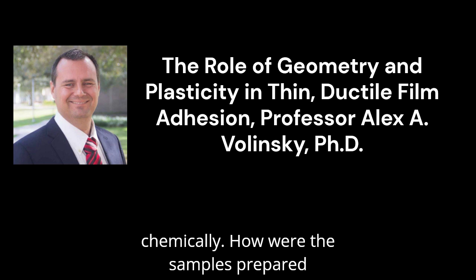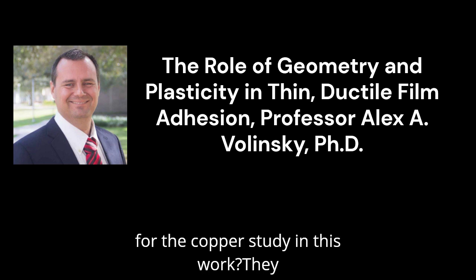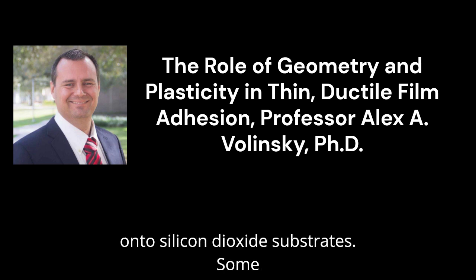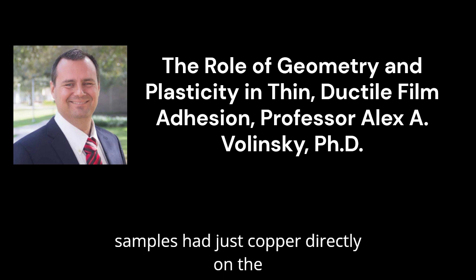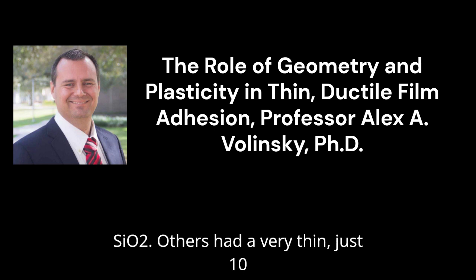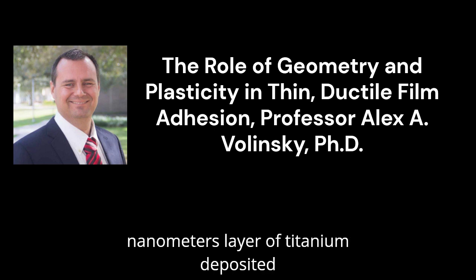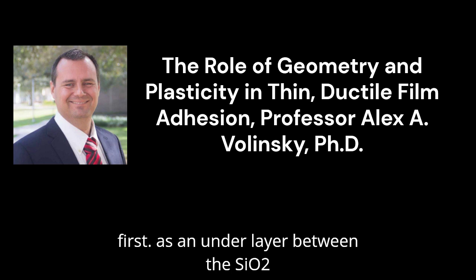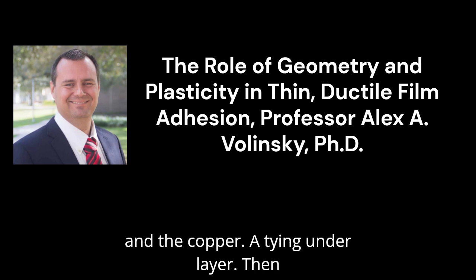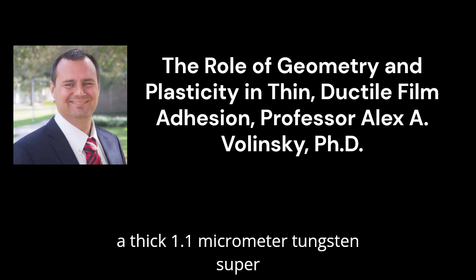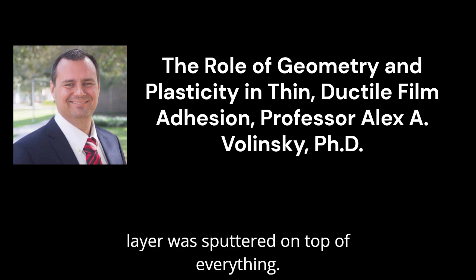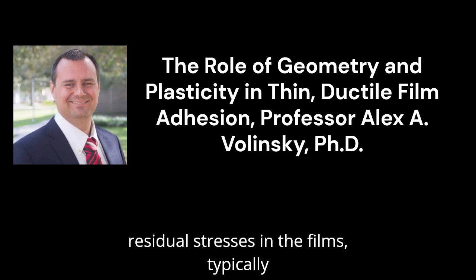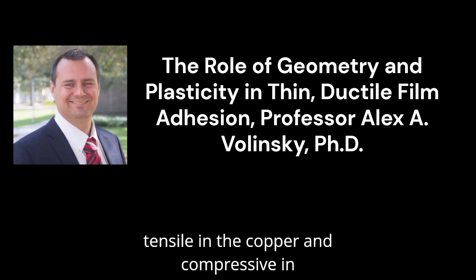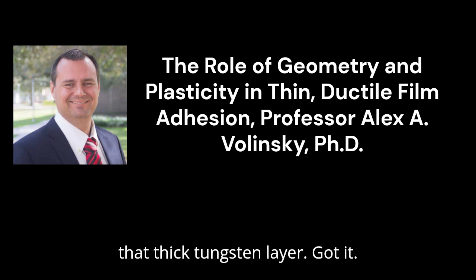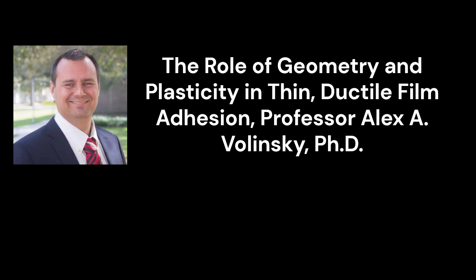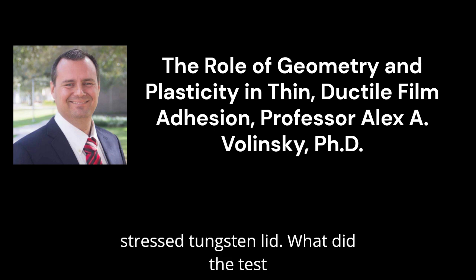Copper can diffuse, it doesn't always bond well chemically. How were the samples prepared for the copper study in this work? They used copper films deposited by sputtering onto silicon dioxide substrates. Some samples had just copper directly on the SiO2. Others had a very thin, just 10 nanometer layer of titanium deposited first as an underlayer between the SiO2 and the copper. A tying underlayer. Then a thick 1.1 micrometer tungsten superlayer was sputtered on top of everything. And the sputtering process leaves residual stresses in the films, typically tensile in the copper and compressive in that thick tungsten layer. Got it. Substrate, maybe a thin titanium helper, the copper layer, and then the heavy, stressed tungsten lid.